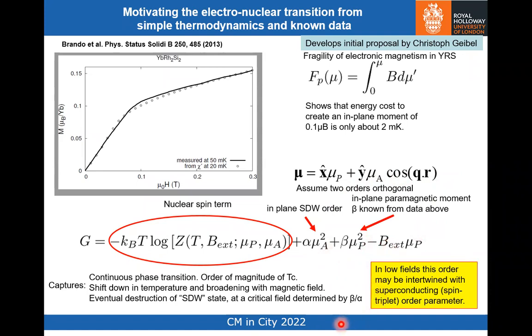I'm not going to go into details, and Jan Knapp is in the audience. I should have pointed him out before. So just to say that this simple experimentalist model captures a bunch of different physics. It captures the fact that the phase transition should be continuous. It captures the order of magnitude of Tc, that the transition should shift down in temperature and broaden with magnetic field. And it also predicts that this so-called spin density wave state will be destroyed by a critical field that's determined by the ratio of these two coefficients.